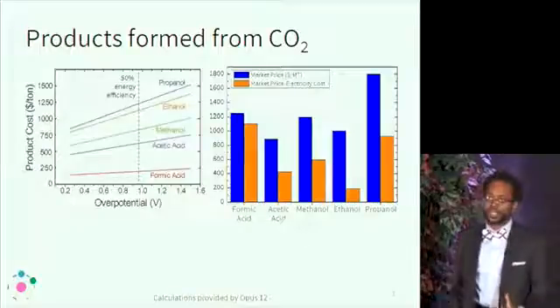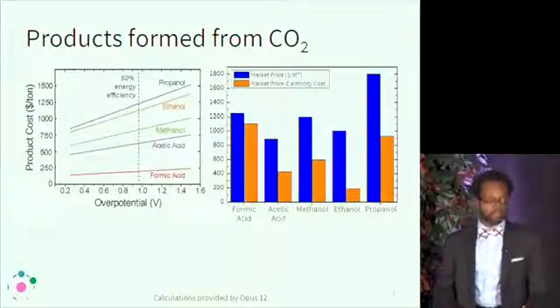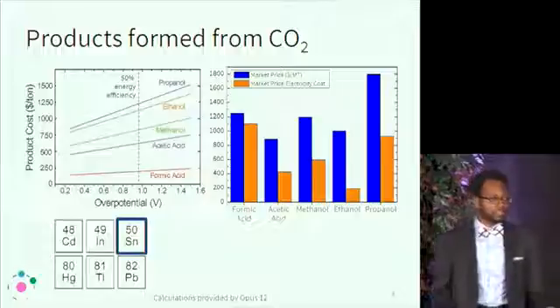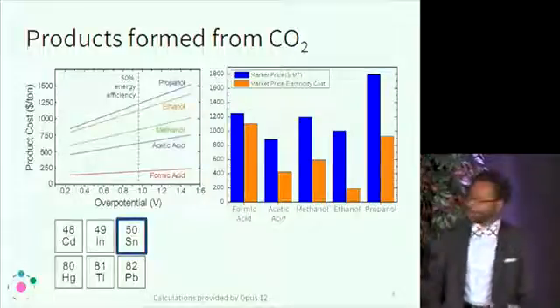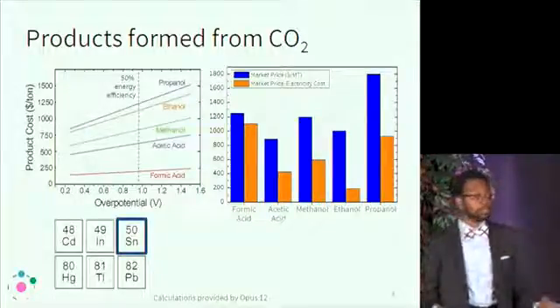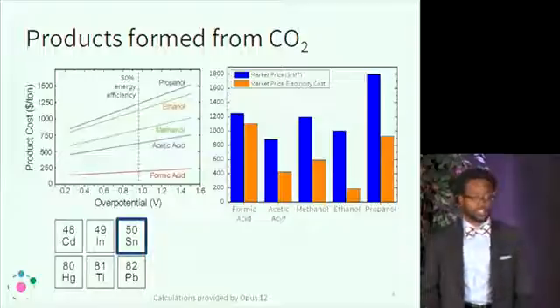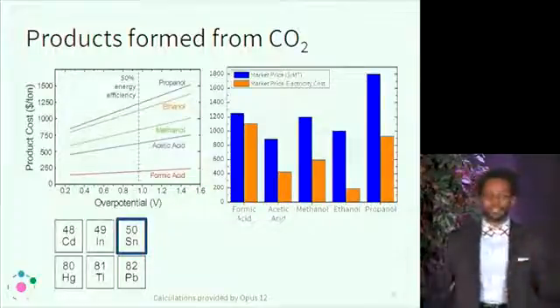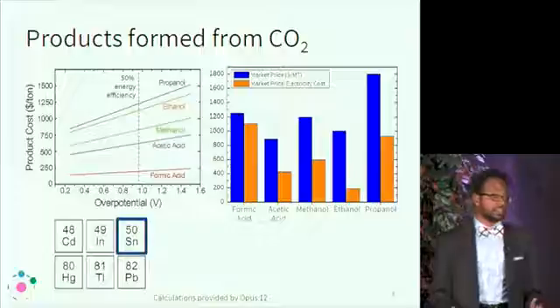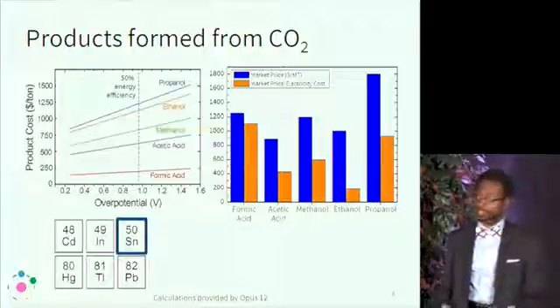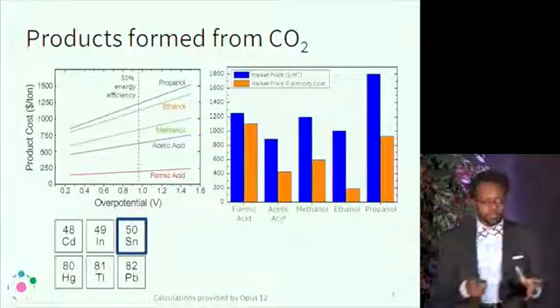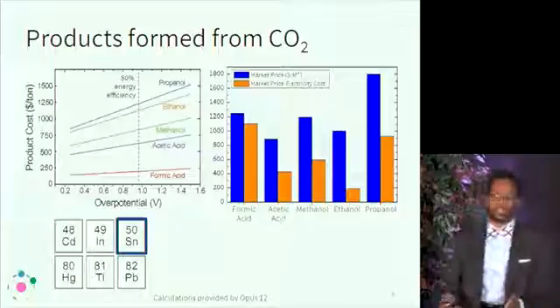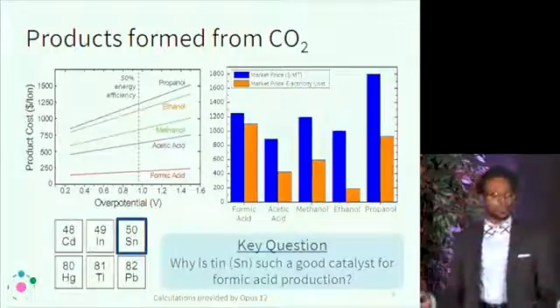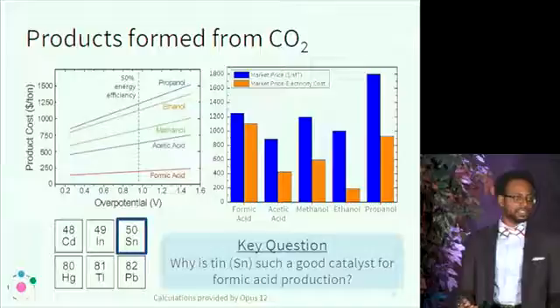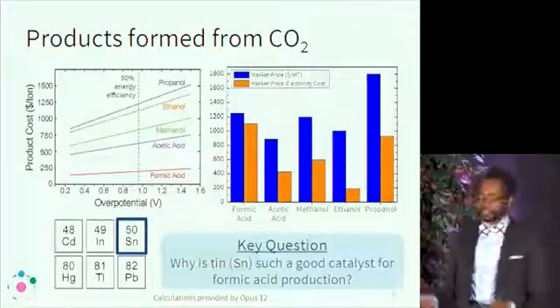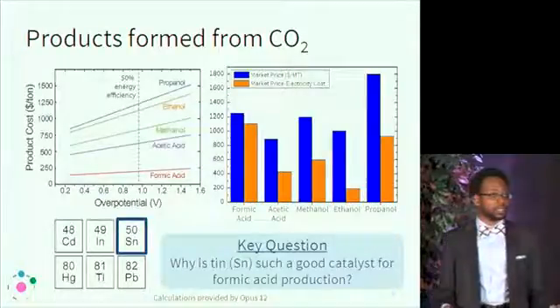So if we're looking at formic acid as the product that we want to focus on, there's a number of catalysts that our field has identified as very promising. Of all of those different catalysts, tin turns out to be one of the more active catalysts for CO2 reduction. And so there's been a lot of good work done on tin catalysts here at Stanford as well as internationally, but there's really one void that we haven't quite been able to answer. And that really is a fundamental question: why is tin so good at making formic acid? That's the key question that I would like to focus on with my work today.